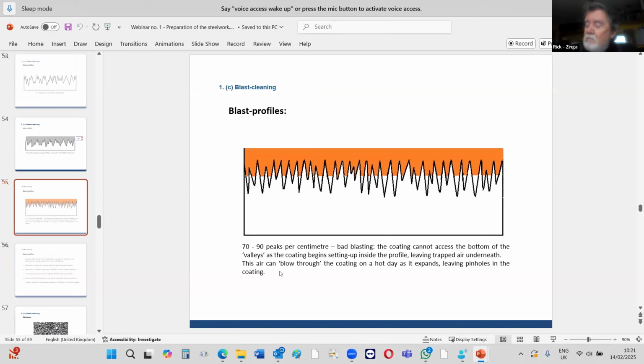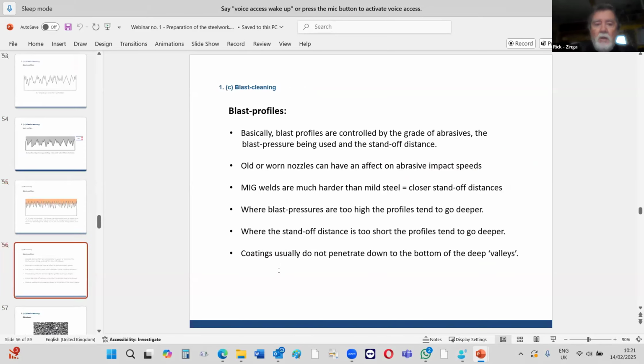And that's what happens if you have, say, 70 to 90 peaks a centimeter. They're so narrow, the coating goes halfway down and it starts drying and it stops. It won't flow right down to the very bottom. This is why the peaks are so important. But the blast profile does that for you. Automatically, it controls the peaks. So you won't have that issue at all.